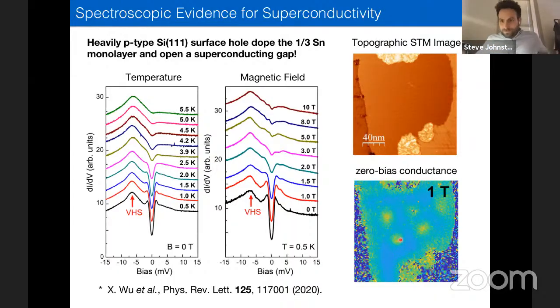So great, superconductivity, and what's the doping here? We think it's about 10%. It's a bit hard to estimate because the only way we know for sure is by integrating the weight in the quasiparticle peak, and there's some uncertainty as to how to count that. You have to fit it with some Gaussians and then look at how much of that spectral weight is inside that peak. But yeah, we think it's about 10% hole doping.